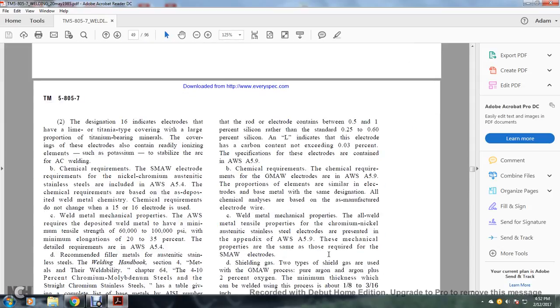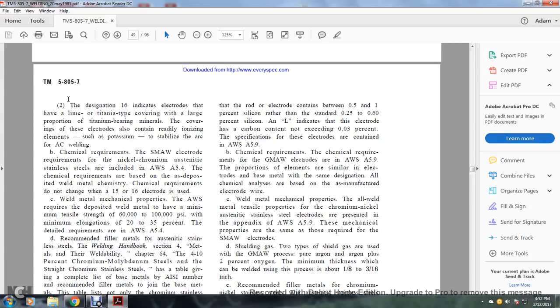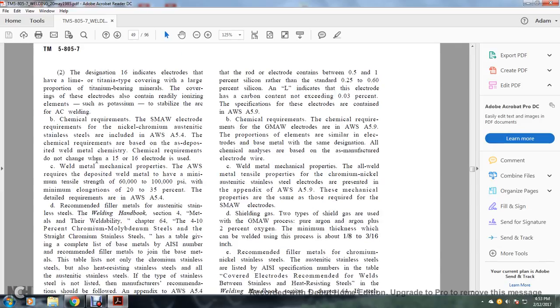The 16 designation indicates electrodes that have a lime-titania type of covering with a large portion of titanium-bearing minerals. The covering of these electrodes also contains readily ionizing elements such as potassium, which stabilize the arc for AC welding. The chemical requirements for nickel and chromium austenitic stainless steel electrodes are included in the American Welding Society A5.4 chemical requirements, based on the as-deposited weld metal chemistry. Chemical requirements do not change whether a 15 or 16 electrode is used.